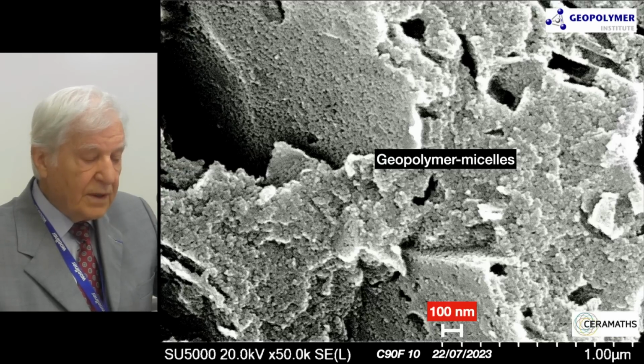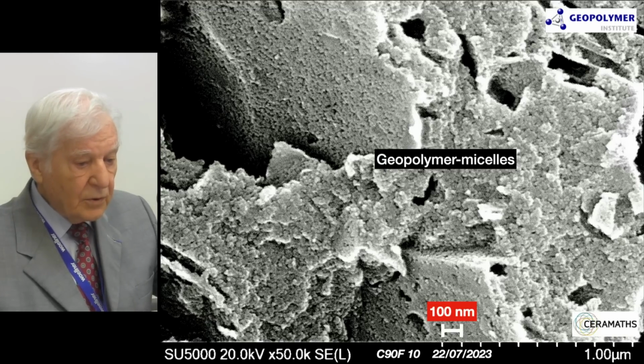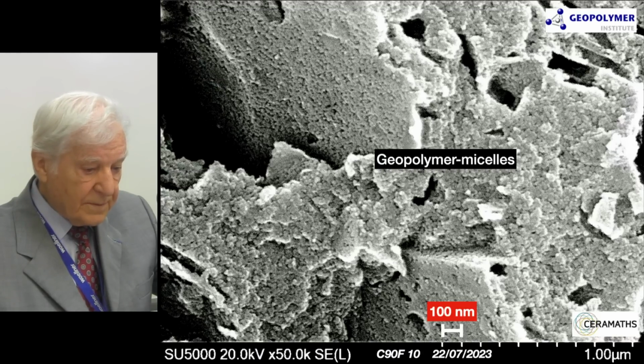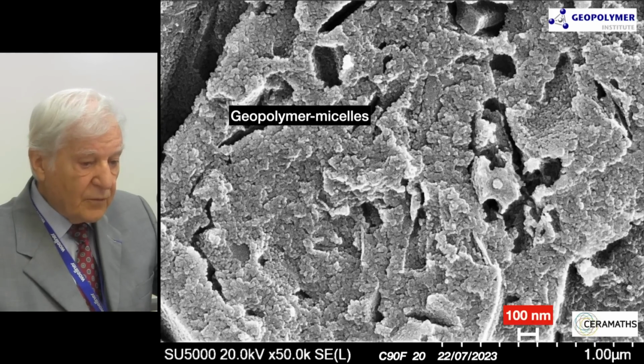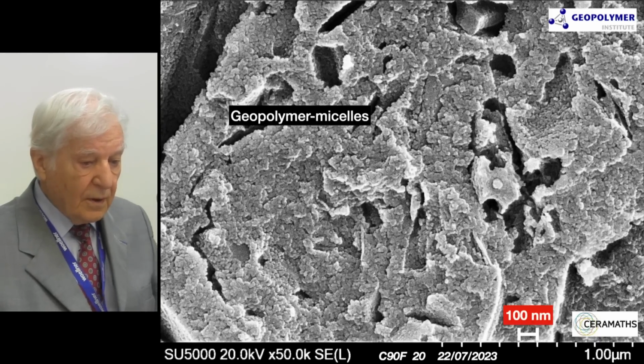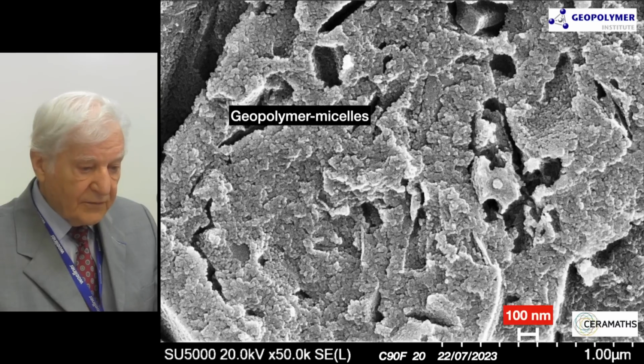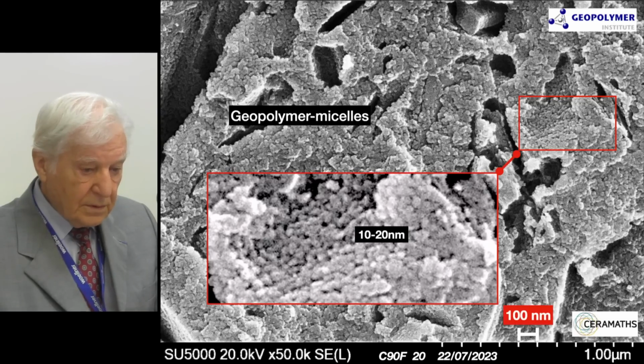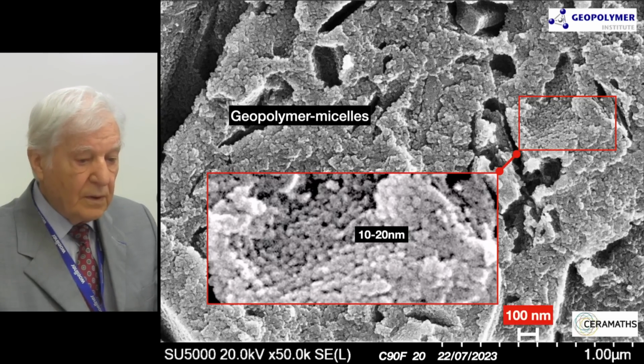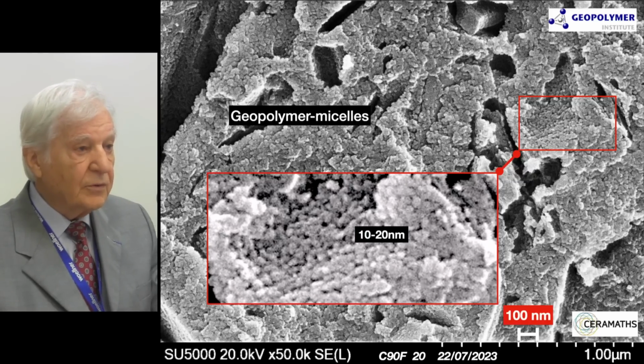After grinding for 10 minutes the liquid geopolymer resin containing potassium silicate and the metakaolin, the matrix no longer shows unreacted metakaolin, only geopolymer micelles. After 20 minutes of grinding, the quaternary structure of the geopolymer micelle is well defined, and the expanded view displays beautiful individual geopolymer micelles with overall dimension in the range of 10 to 20 nanometers.